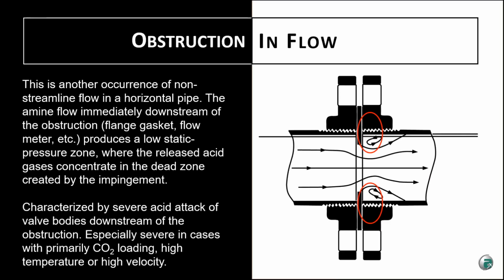This is another example of non-streamlined flow caused by an obstruction in a horizontal pipe. The obstruction causes a reduction in flow area, which means that you generate a vena contracta, and at this location you can break out acid gas. The acid gas tends to migrate just past the obstruction, and in this case it's the downstream side of a valve body, and in many cases we get very severe corrosion of the valve body downstream of that obstruction. And this is especially severe in cases where we have high CO2, high temperature, or high velocity.